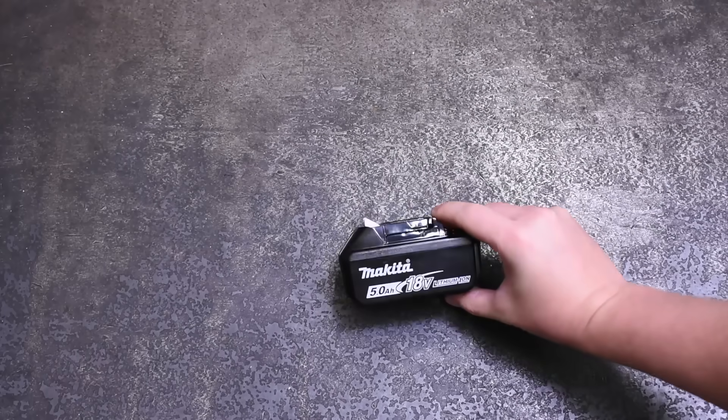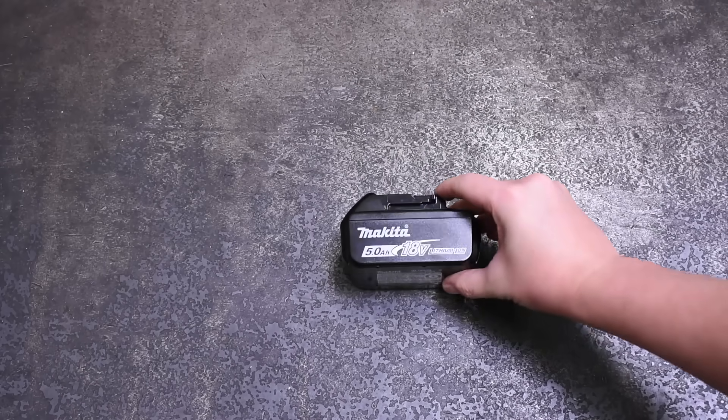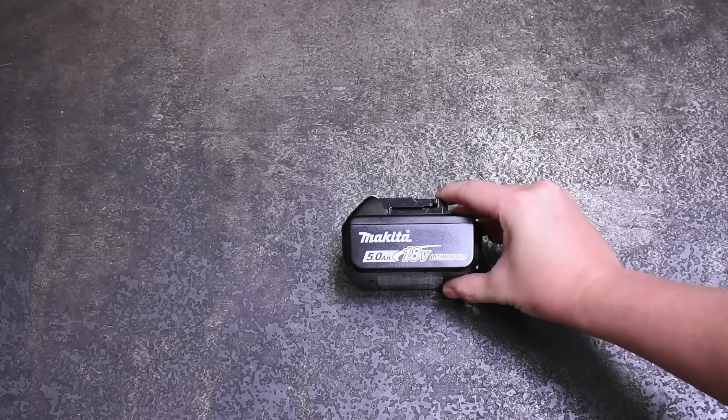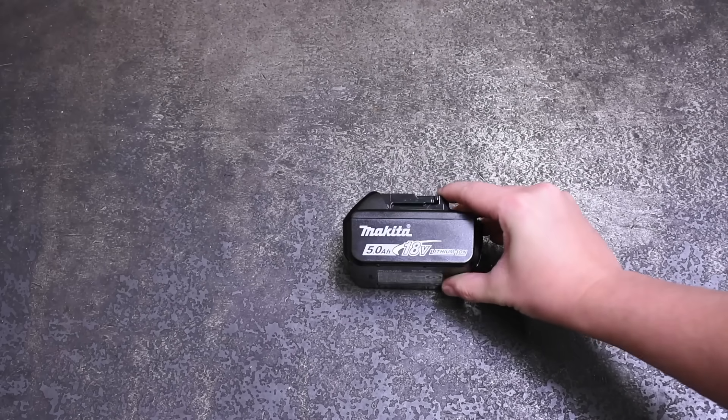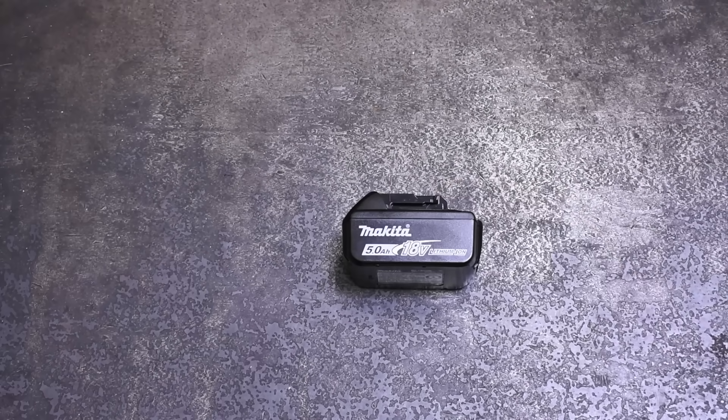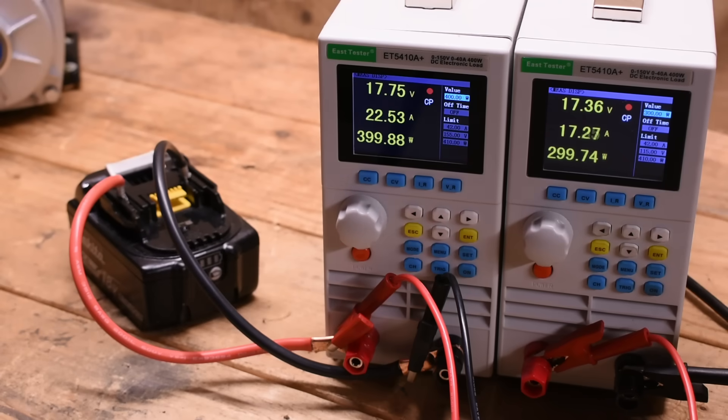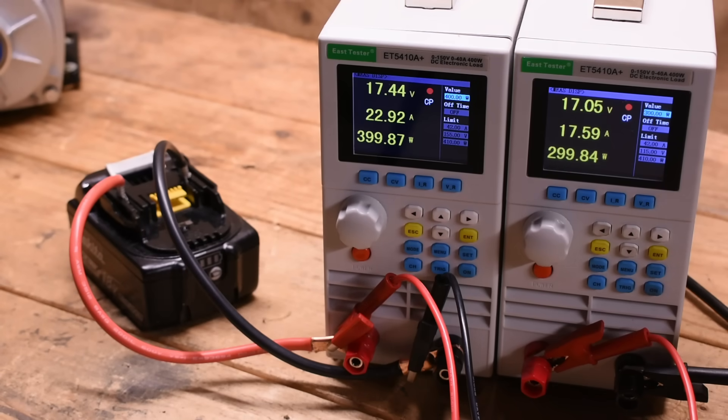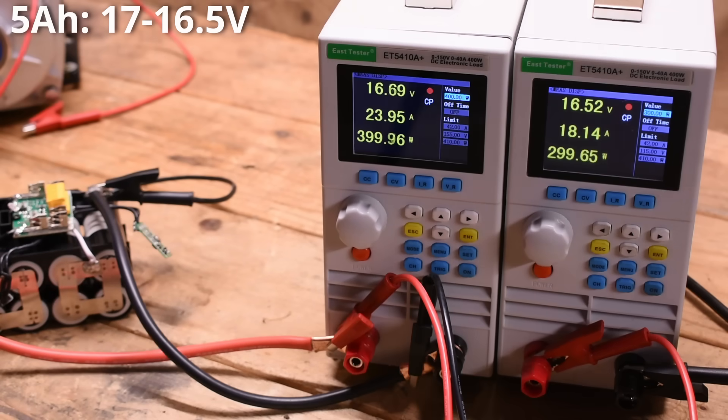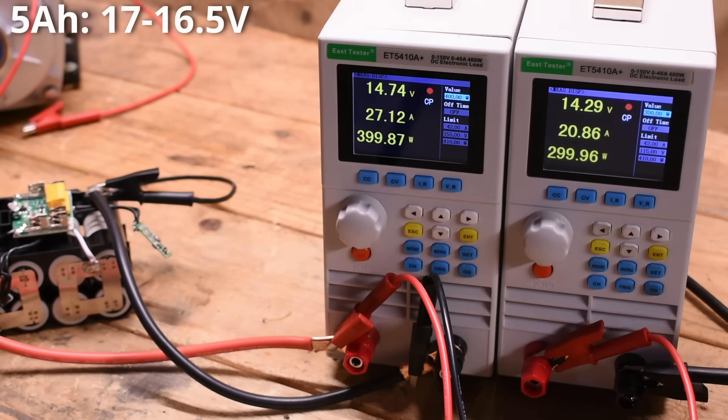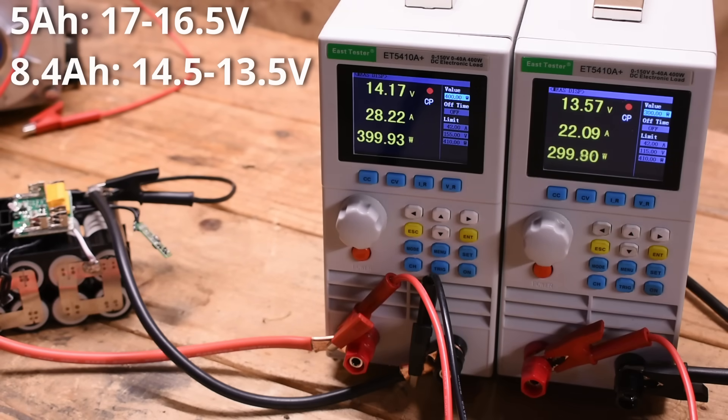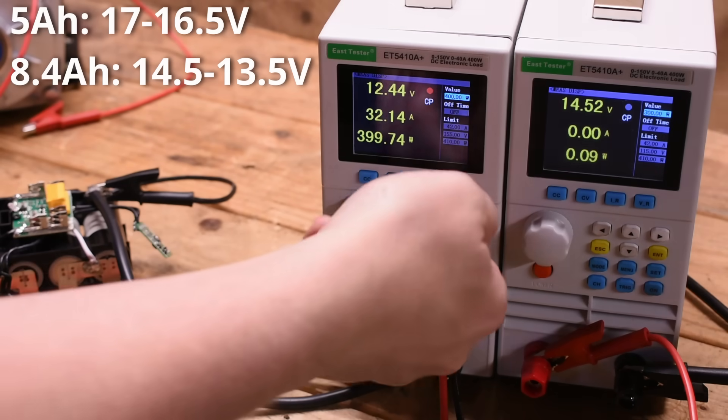Let's take a look by drawing a quite heavy load of 700 watts from a stock battery. We can see its voltage drop here to around 17, 16.5 volts. Now that performed on our creation with the case off to see what's going on, that voltage drops down to 15, 14, 13.5 volts. Oh, and this thing started smoking as well. Turns out it was burning through the metal connections.